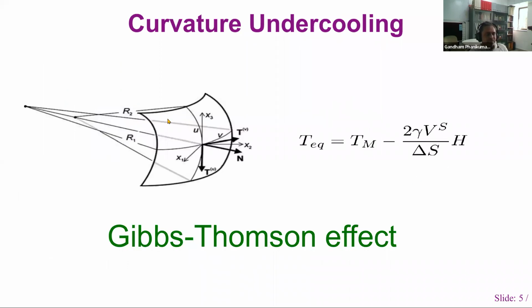Now, the next driving force comes from the curvature of that dendrite tip. You have seen in the videos I have shown that the dendrite is tree-shaped, so the curved nature of it will also give you some driving force. And the H here is basically the averaged curvature. It is called the trace of the curvature tensor, and gamma is the surface tension. This is the molar volume of the solid phase, and delta S is the entropy of fusion. Tm is the melting point, the temperature of equilibrium between the curved dendrite and liquid. So what I want to convey here is that if you have a dendrite that is very fine, there is more driving force, and if the dendrite is very fat, it has less driving force for solidification. That's what you can convey from here.